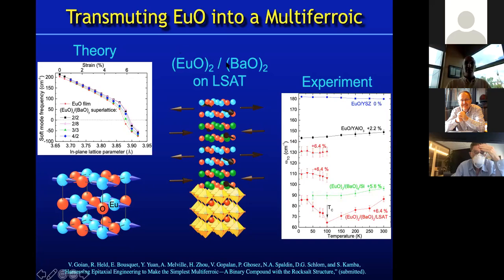The method that worked for him was to make a superlattice with just 2 unit cells of europium oxide and then 2 unit cells of barium oxide. So it's like a strained layer superlattice. The strain is going back and forth and back and forth. The whole thing is grown on LSAT, so the entire structure is commensurately strained to the underlying LSAT substrate. So that imposes a strain on both the europium oxide and the barium oxide. And on the europium oxide, it's over 6%.